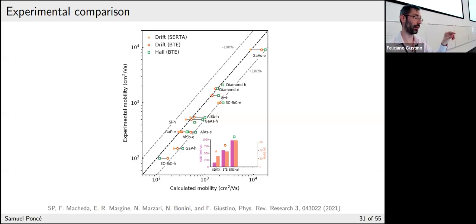So what you can do is simply rescale your matrix element by multiplying and dividing by the experimental dielectric function, if you know it, and the one that you compute. This will rescale, and you will get a bit closer to experiment. So that was one thing.